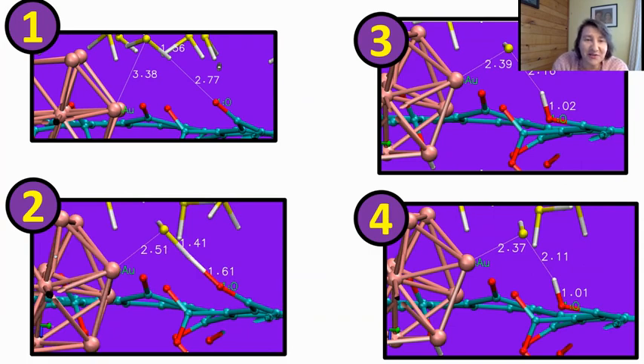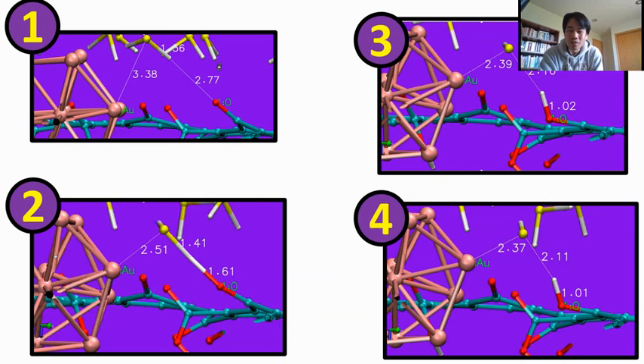I was talking about the stability of the gold cluster in graphene. Let's assume that the gold cluster is already stable and has decent stability. Gold 13, to my knowledge, is quite stable as an atomic cluster. So assume you don't have to worry about that part. We just worry about whether that piece of graphene can hold the gold cluster, because you have to make the hole and put the gold cluster into that hole.